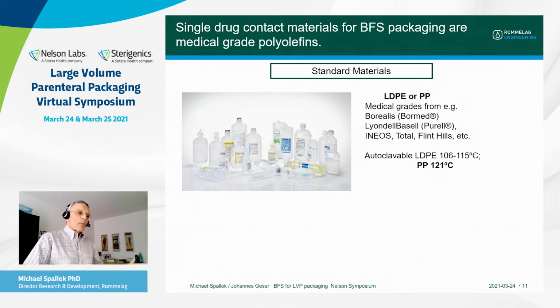The most important selection criteria between LDPE and PP certainly are the requirements for terminal sterilization. This is typically done by autoclaving. And if you have a product that needs a high autoclaving temperature as recommended by the authorities, then polypropylene is a good choice. Whereas if you have a thermally not that stable formulation, LDPE would also do a good job.